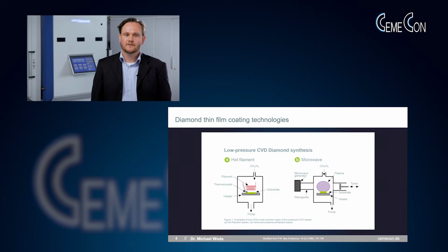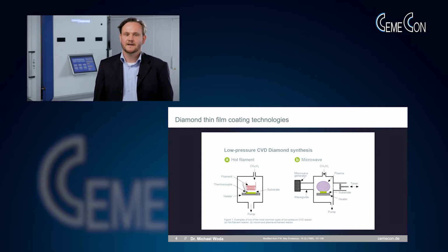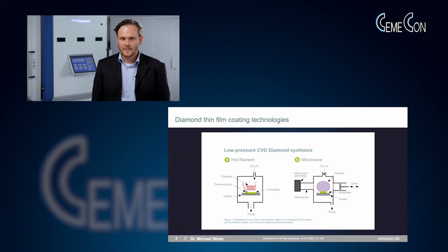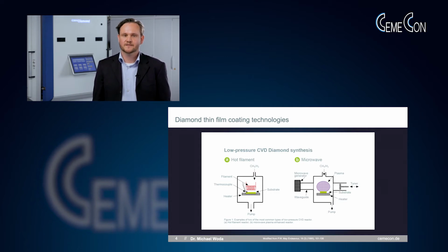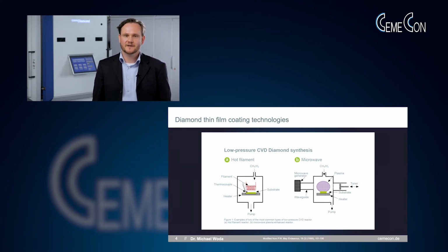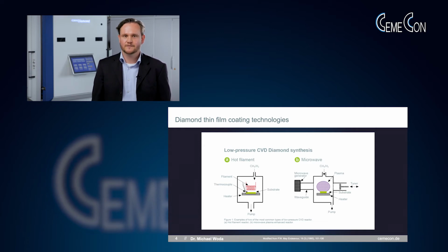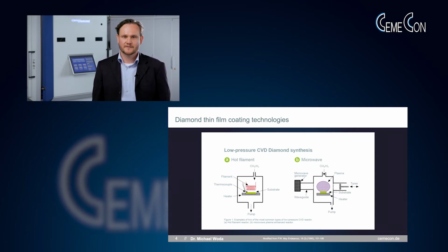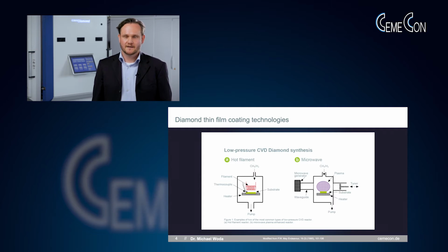In this schematic view graph, we can see the two major coating techniques for diamond. On the left-hand side, we've got hot filament CVD, and on the right-hand side, we've got microwave CVD. Both techniques have the same basic setup. We introduce a hydrogen-methane gas precursor mix into a vacuum chamber and have a source for the activation of energy to allow the chemical reactions. In the case of hot filaments, we've got the filaments providing thermal energy to the reactor. In the case of microwave, we've got a microwave generator which ignites a plasma in order to transfer the energy to the process. Both techniques have their benefits. For the use on cutting tools with complex geometries, hot filament is the method of choice.